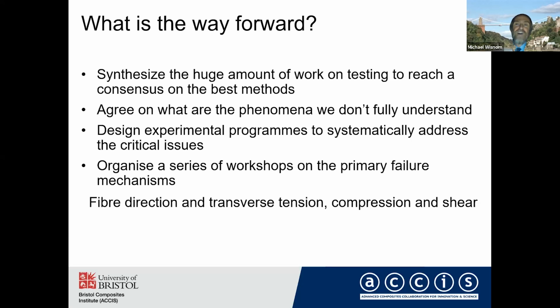But also rate effects are important in compression as well because, again, it's matrix dominated and the rate effect does affect the matrix performance. So you definitely need to be aware of those and to make sure that your test results are consistent with how you want to use them.